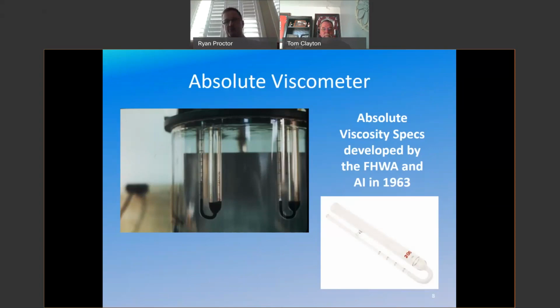First of all, you put the sample in a bath, you look on the right there, and you can run a viscosity at a variety of different temperatures. Typically, we would run these at 140 degrees Fahrenheit, or we would run them a similar viscosity at 275 degrees Fahrenheit. And you use a vacuum to start the asphalt going, and you measure the time that it takes to go in between two marks on a vis tube, and you run it a couple of times on the same vis tube and take the average. And the thought on this test is that the lighter, the less viscous the material is, the faster it flows through the tube, the heavier it is, the longer it takes.